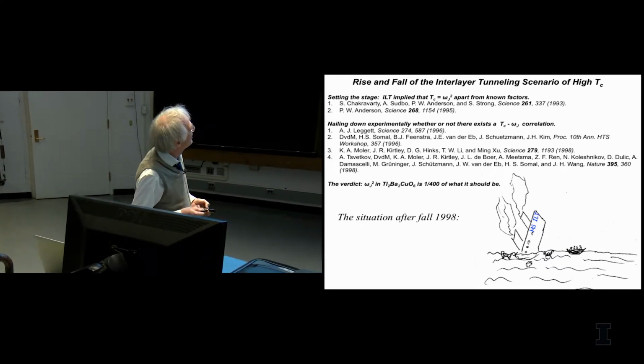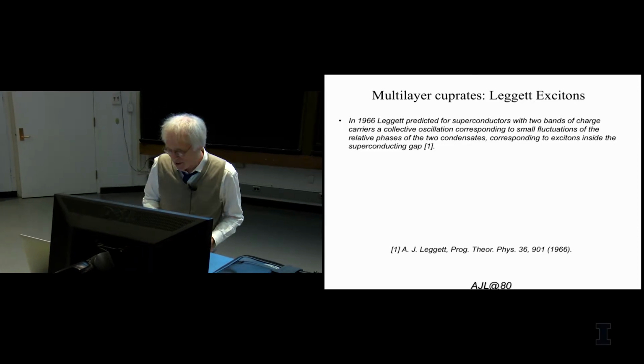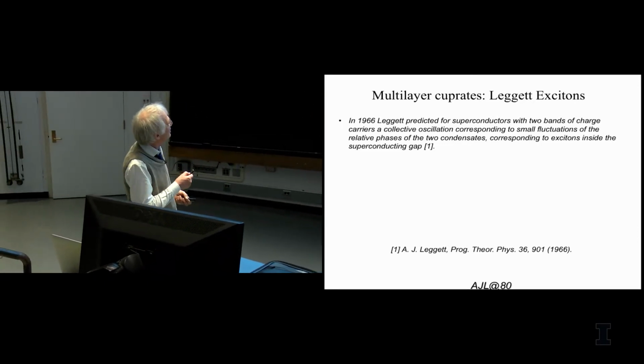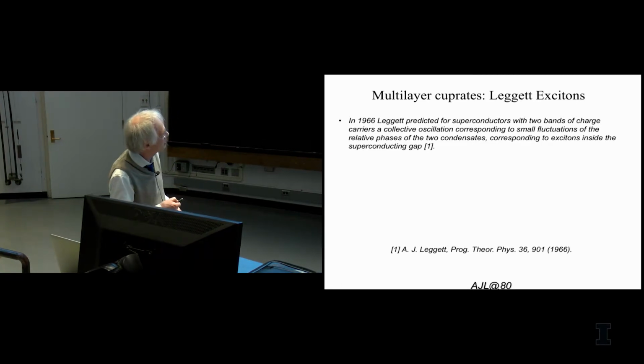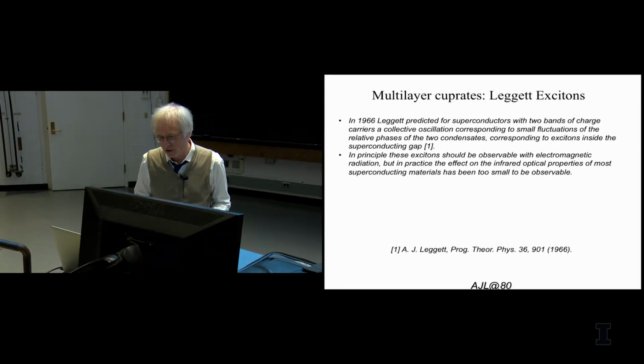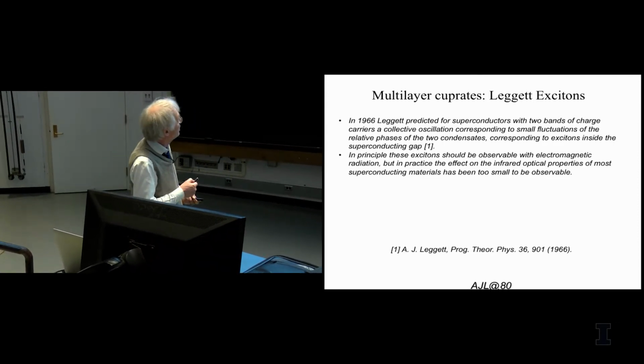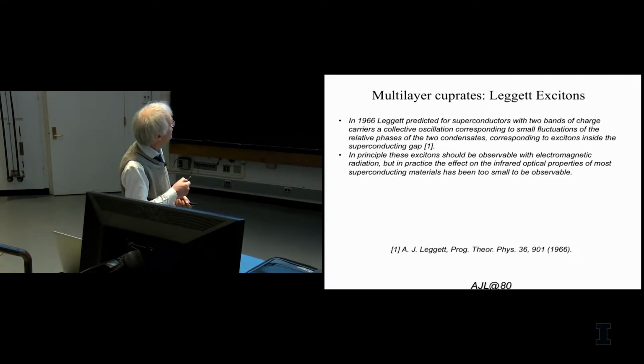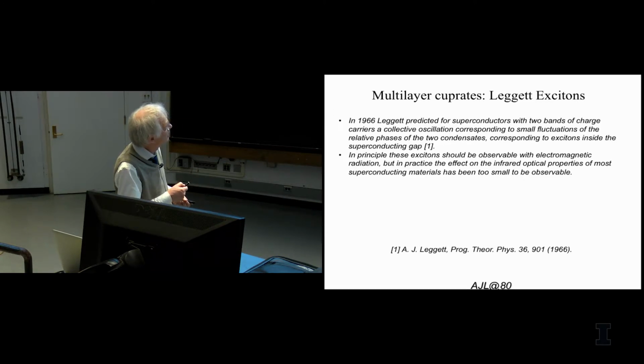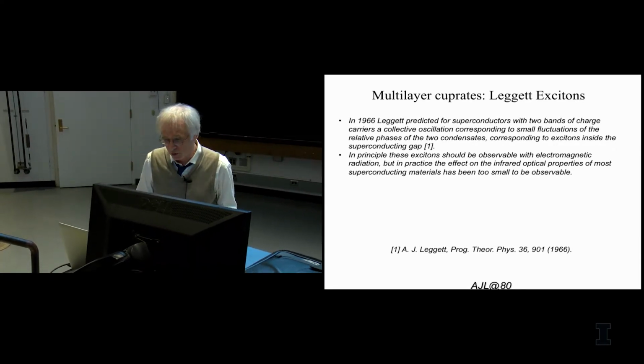Yeah. So now we get to multilayer cuprates, and that's actually where another story comes in. In 1966, Leggett predicted, for superconductors with two bands of charge carriers, a collective oscillation corresponding to small fluctuations of the relative phases of the two condensates that form inside the two bands. And that corresponds to a kind of excitons inside the superconducting gap. This is the paper. It's a long paper, but the message itself is quite simple, actually. In principle, those excitations should be observable with electromagnetic radiation, either Raman spectroscopy or infrared, depending on details of the material. But in practice, that effect on the infrared optical properties of most superconducting materials has been too small, probably too small to observe. But there's an exception.